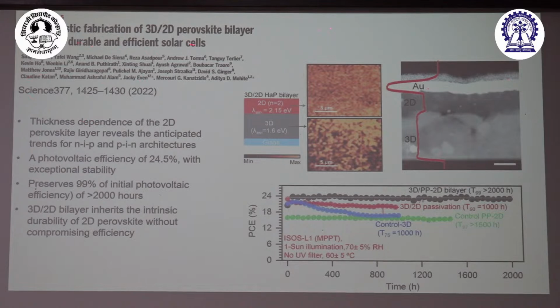The title, bilayer durable and efficient, okay? And they showed that, well, we have got this stable thing for 2,000 hours. Again, in all these stability curves, you see the time scale changes; sometimes people put 100 hours, sometimes people put 500, because after that they start degrading, okay? That's why they didn't give you more time. But anyway, in this case, they showed you this 2D layer on top of 3D layer, cross-section analysis.